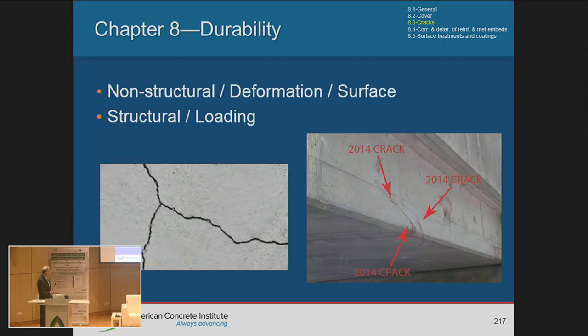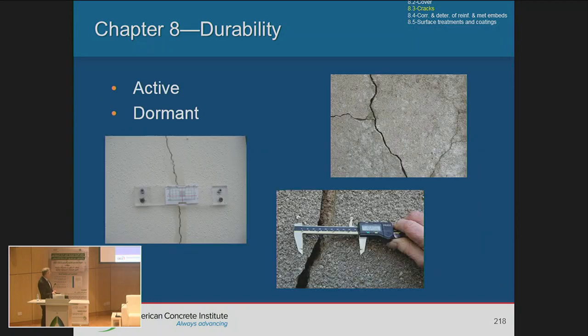For example, here on the left side, where you have random cracks, could be just from shrinkage and temperature. Those may not be as critical as when you have those inclined cracks at the edge of a girder or a beam. That means here we have shear cracking. That needs to be addressed, and that will affect your strength.